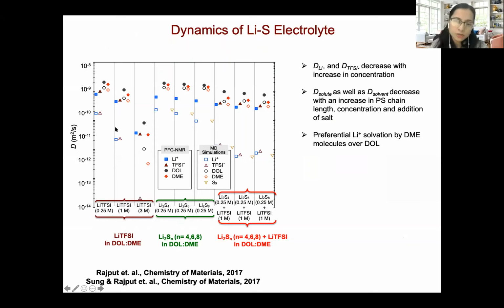Okay, so for the first variable, we found that as we are increasing the salt concentration, we are going to decrease the mobility of different ionic species in the solution. And just to let you know, this plot shows the self-diffusion coefficient data of lithium TFSI, solvent, and polysulfide using experiments as well as simulations. Okay, so we found that as you're increasing the salt concentration, the mobility goes down, which is kind of expected, but we found that at particular 3 molar concentration, we are looking at almost a 2-order decrease in the mobility of ionic species in the solution. So if we keep on adding more salts, it's going to impact the mobility of ionic species, which can affect the conductivity of the ionic species.